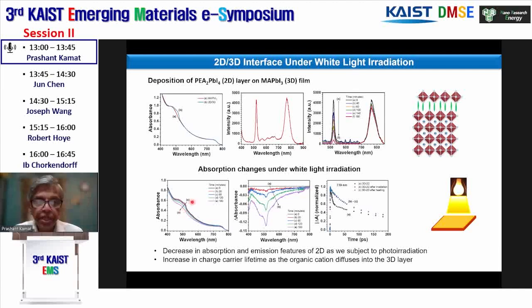We can follow this absorption change under light, and you can see here, this 2D peak decreases. This is shown in the absorption here. The bleach, the difference absorption, increases, and we can follow and get the kinetics and everything. More interestingly, if you do a transient absorption to follow the carrier lifetime, you see that after putting this 2D layer, they become better, but even after irradiation, it doesn't change. So it agrees with what people have seen, that putting 2D layers improves the performance. Even after shining light, it doesn't change. It retains the improved condition.